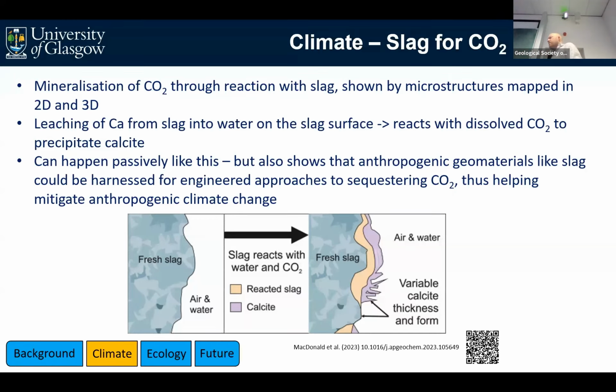And so, we collected this data just by looking at slags that have been dumped, left in a heap near the steelworks. And that's just happened passively. But actually, there's a lot of research ongoing that shows that you can take this material and engineer that process to speed it up, maximizing the amount of CO2 that you can mineralize. So it presents an interesting opportunity as an anthropogenic geomaterial for maybe offsetting or mitigating some of the effects of anthropogenic climate change in terms of the amount of CO2 in the atmosphere.